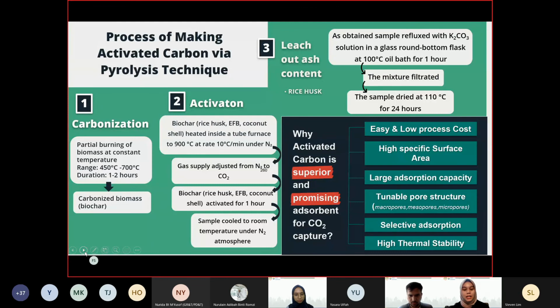In the second stage of the process, biochar is then heated in a tube furnace with nitrogen gas, which is then adjusted to CO2 gas. Biochar sample takes 1 hour of activation process and it is cooled down to room temperature in the presence of nitrogen gas. In the final stage, the sample is refluxed with a potassium carbonate solution and the mixture is filtered and dried. Activated carbon is so promising and superior due to these qualities that we made it our focal point in our project.